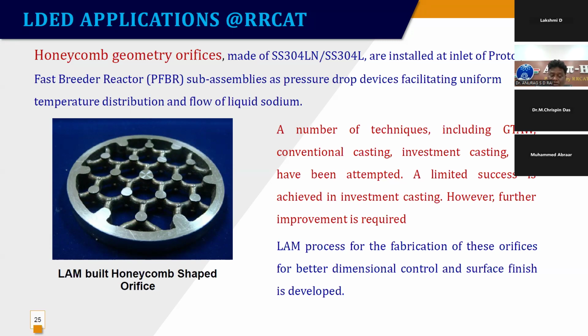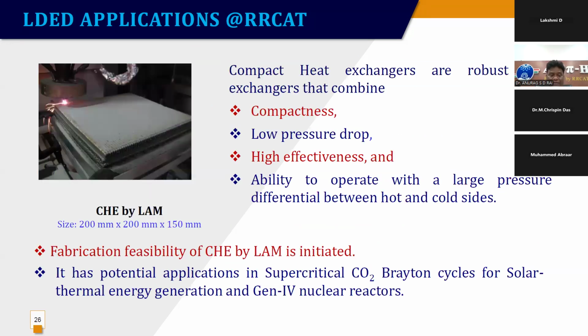These honeycomb shaped orifices are placed one after another, and by just tilting by 15 degrees, you will see two consecutive honeycomb shaped orifices. See the bars, which put the pressure drop on the path, more resistance, and that way the flow of the liquid sodium is controlled. So this is done, and a lot of things can be tried out using this.